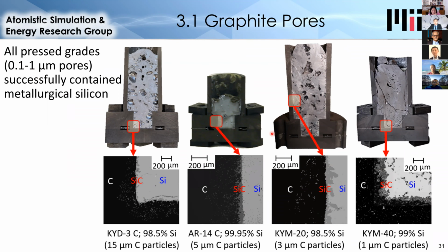And so this showed that basically any pressed grade of graphite, which has pore sizes up to 1 micron, can be used to successfully contain silicon even up to 2300 degrees Celsius. This is very important because these grades of graphite are just a few dollars per kilogram, between about $2 and $7 per kilogram, whereas very high quality grades of graphite can be up to $1,000 per kilogram.